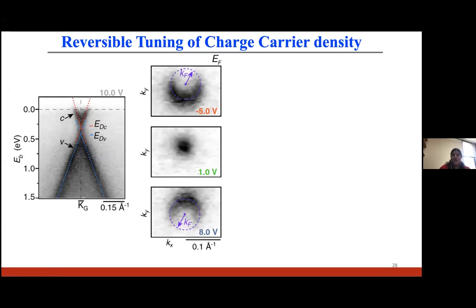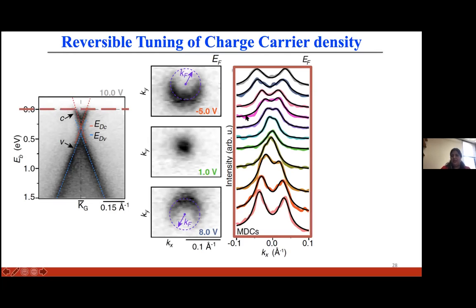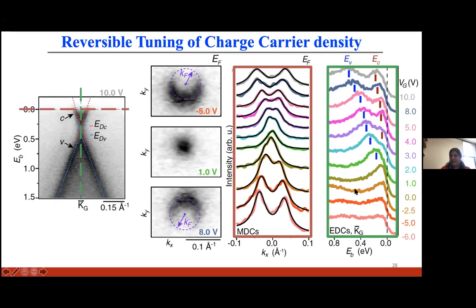Okay, so what I'm showing here is a graphene Fermi surface at a few gate voltages. And this radius here, Kf, determines the size of the Fermi surface. We can extract this by taking a line cut at the Fermi level, the Fermi surface, and plotting these MDCs, which I'm showing here. From the separation between these two peaks, we can extract this radius Kf. And furthermore, I can track these two crossings, the conduction band and the valence band crossing, by taking a line cut along this green line here. And I can plot these EDCs, which I'm showing here.